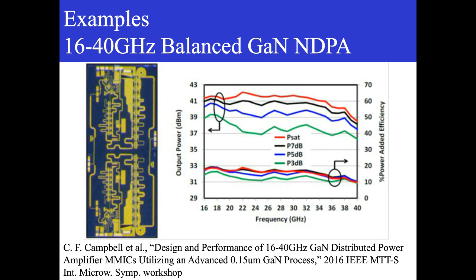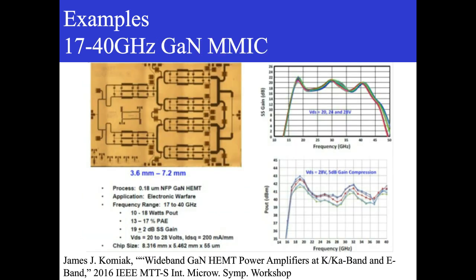So here I'm going to show just two quick examples of MMICs, very impressive examples. This MMIC covers 16 to 40 gigahertz, puts out more than 10 watts across the entire band, and has power added efficiencies between 10 and 20%. So you can see what can be done with a nice gallium nitride process. Here is another example. This one is from BAE, and again, you can get roughly 17 to 40 gigahertz with 10 to 18 watts and 13 to 17% power added efficiency with excellent gain. And you can see that the uniformity is excellent. So from one part to the next, you're able to reliably get the performance.